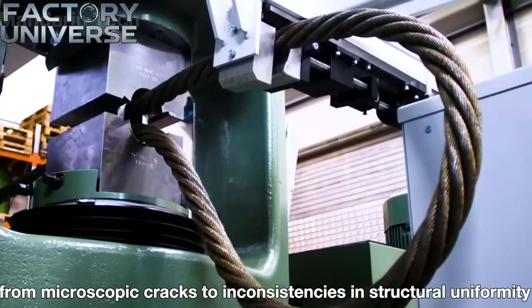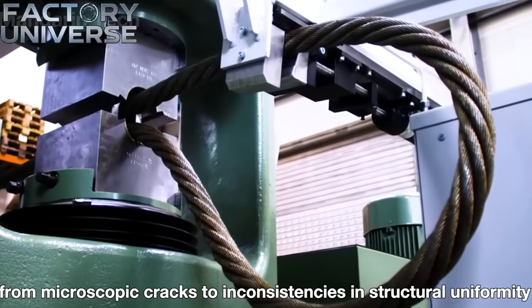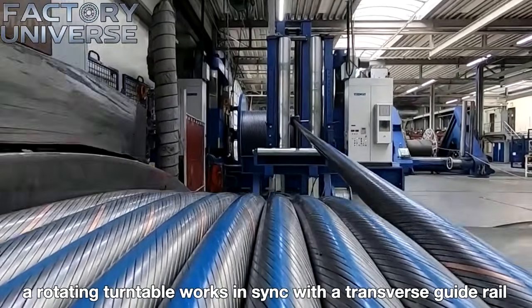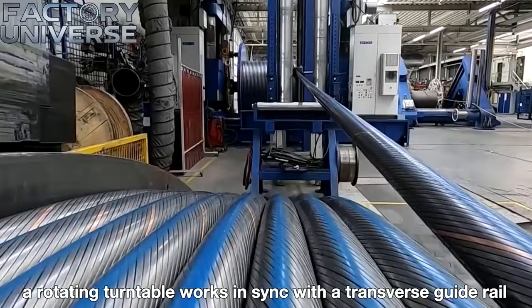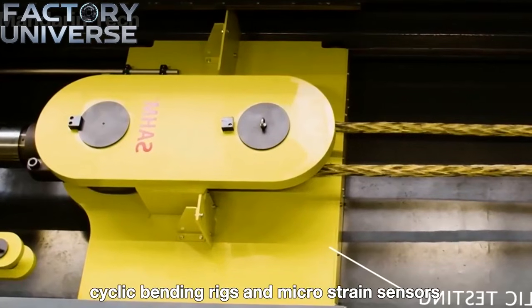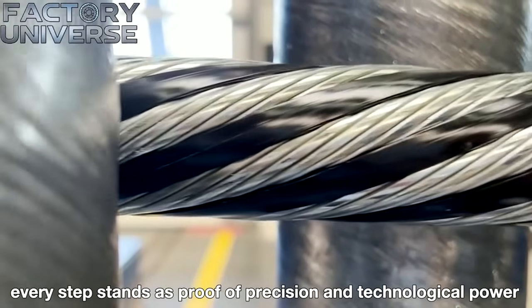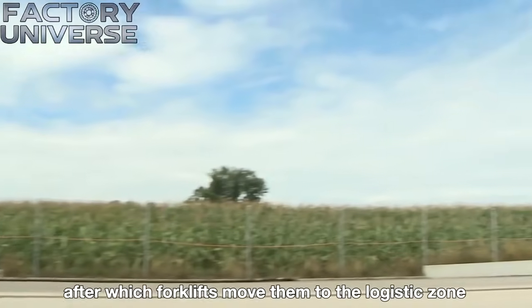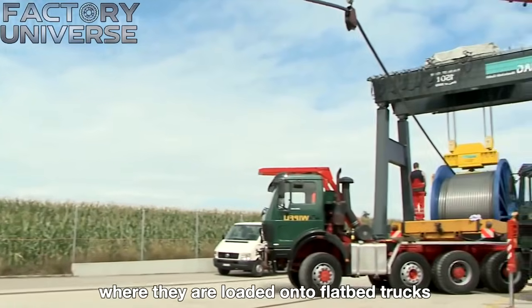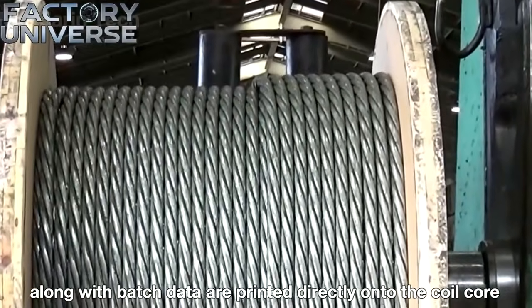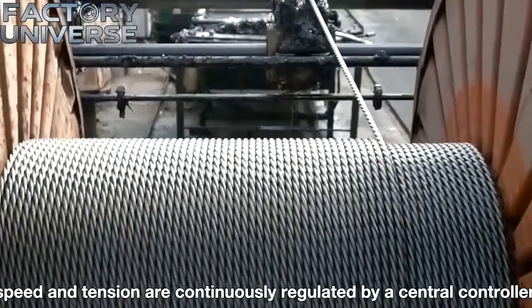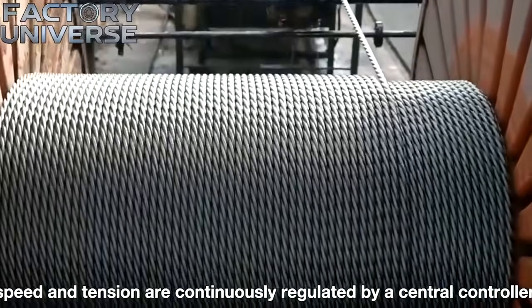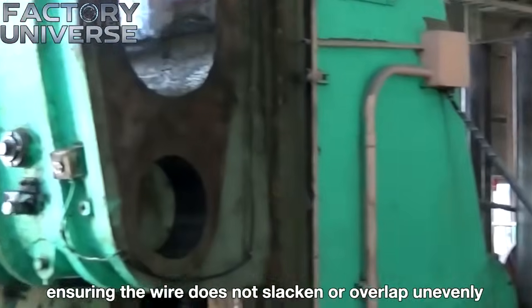The testing phase begins as large-scale hydraulic tensile machines grip the steel strands with immense force. The cable is pulled continuously with increasing pressure until the metal reaches its true load-bearing limit and eventually snaps. Cyclic bending rigs then subject the material to repeated twisting and flexing under varying atmospheric loads to simulate years of service in severe environments.